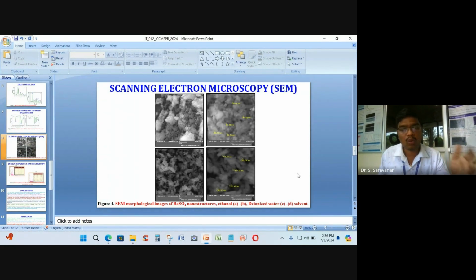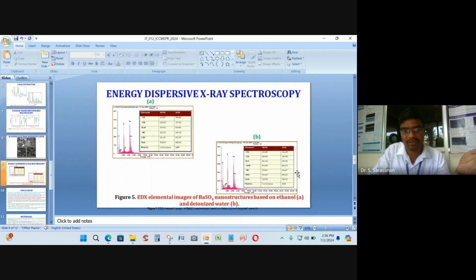Here, I'm not only changing the solvents but also the molar ratio. For ethanol I have used 0.05 molarity, and for DI water I have changed to 0.1 molarity concentration. So these are the differences in how the growth happens.